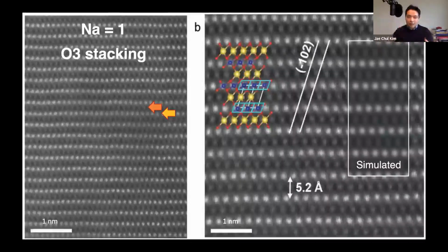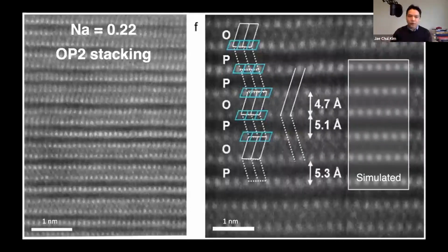This is a fully discharged state. So, pristine material. What happens if the material is charged? This sample is obtained at a high state of charge. You see the difference now, right? You still see the same transition metal bright spots, but now you do see two different sodium layers, which indicates that sodium sits in octahedral sites as well as prismatic sites.